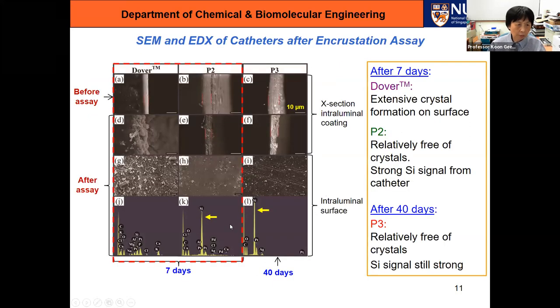So we tried to confirm by looking at SEM and EDX of the coating. So the first row shows the cross-section of the coating before the assay. So the Dover catheter has a thinner coating than ours. And the second, third, and fourth row will be after the assay. First two columns for Dover and P2 for 7 days. Last column for P3, which is our best performer, is 40 days. So you can see that after 7 days, we can't even see the coating anymore because it's totally encrusted. And you can see from the top surface, lots of crystals around. If we check EDX, the silicon signal from the substrate, because we're using silicon catheter, has diminished so small. And in place, we start to see calcium and magnesium.